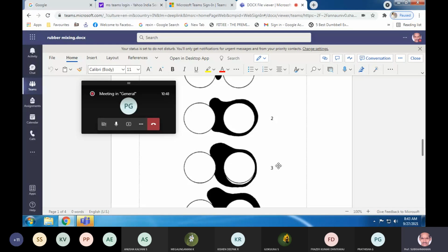As a result, their surface energy is reduced. In case of the rubber, surface energy is enhanced; in case of the powder additive, surface energy is reduced. So there is a point at which these two match and we get a homogeneous mix within a reasonable time and energy of mixing.